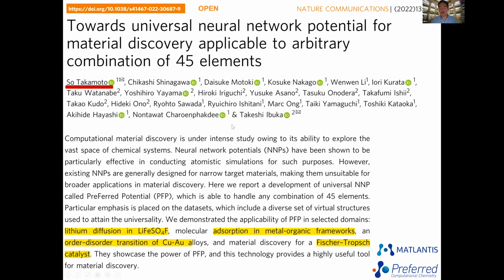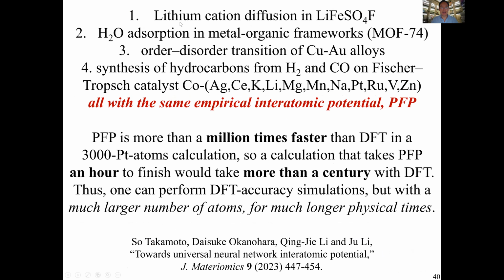So the point is that we're able to do this all with the same neural network. And so Sō went back to Japan. He joined the leading AI company, Preferred Networks in Japan. And he put together a big team of developers, and we basically generalized this to the whole periodic table. And in this Nature Communications paper, they show four examples: lithium cation diffusion in a cathode material in lithium-ion batteries, molecular water adsorption in metal organic frameworks, MOF-74 with different metal centers, order-disorder transition in binary copper-gold alloy, and then synthesis of hydrocarbons by Fischer-Tropsch synthesis using hydrogen gas and carbon monoxide based on these multi-metallic catalysts.